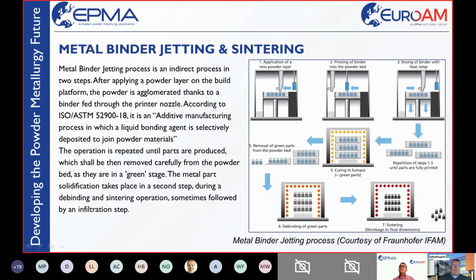It's also a powder bed based process. So you're preparing a powder layer, the print head comes and prints binder into the powder bed, then you have a small drying of the binder in between, and then you repeat these steps: powder layer, printing binder, drying. In the end you end up with so-called green parts.